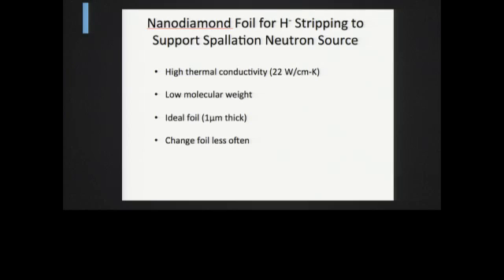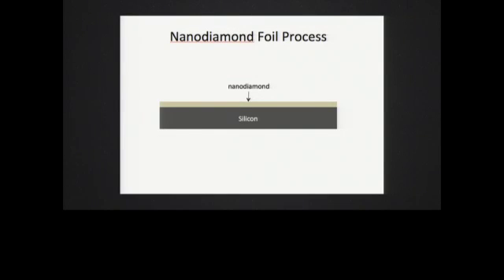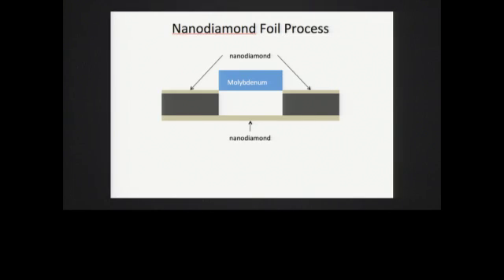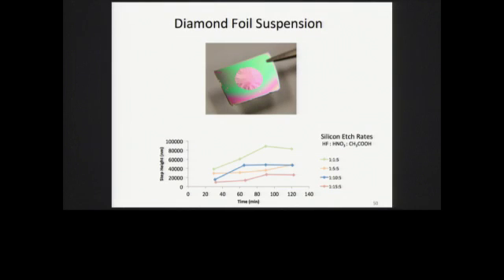You also have to have a low molecular weight. The foil has to be very thin, and the foil should change very little depending on the source of protons that hits it. So we developed a process of making thin film nano diamond on silicon, and we use molybdenum on the backside. We thin it down, we anneal it to remove some of the stress, and we can make transparent thin films of 1 micron or less of diamond on top of silicon substrates.